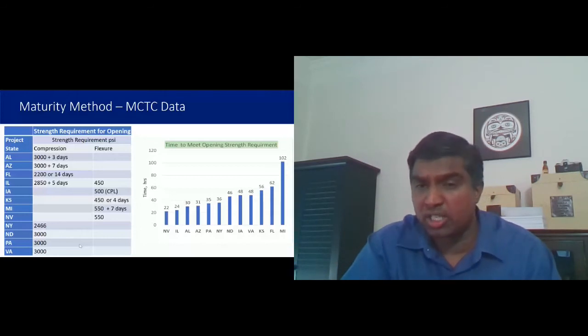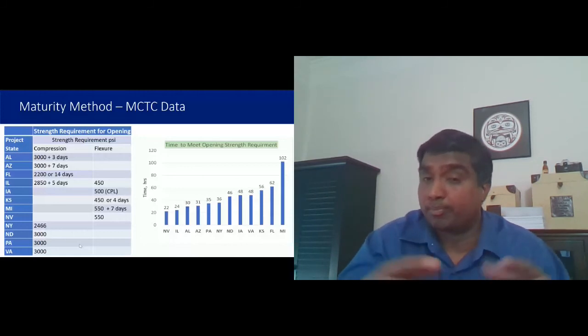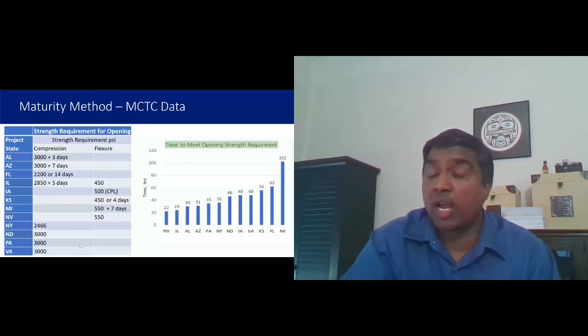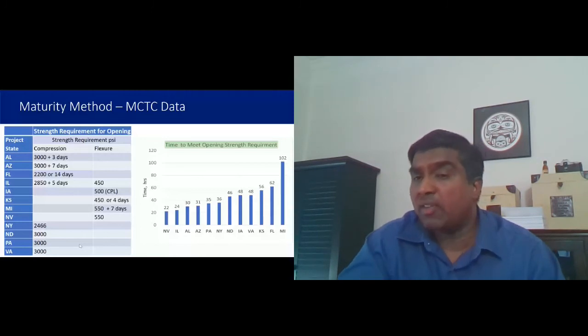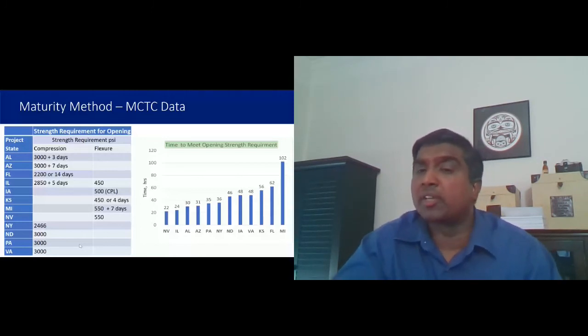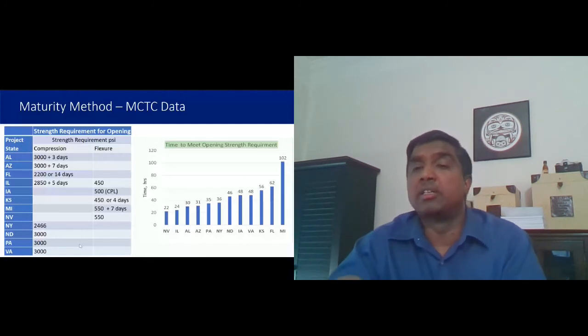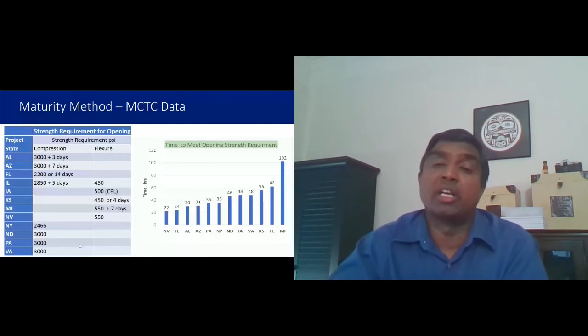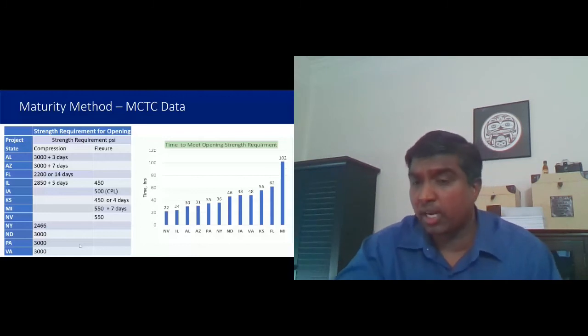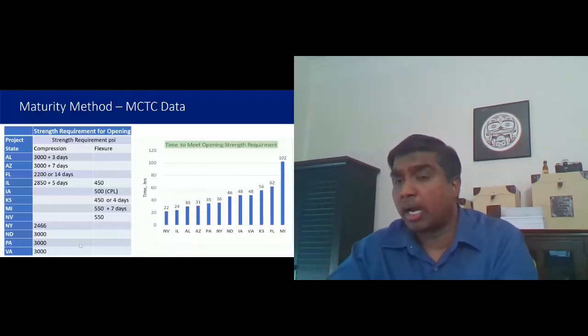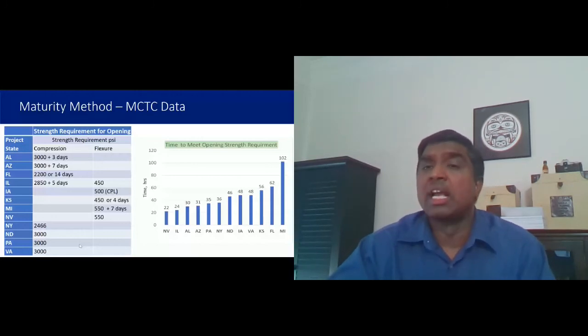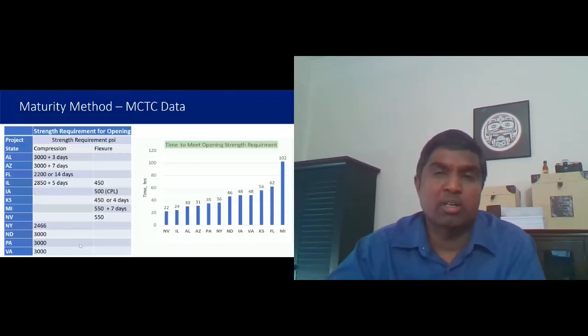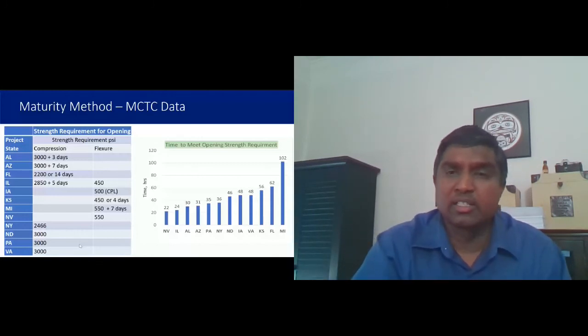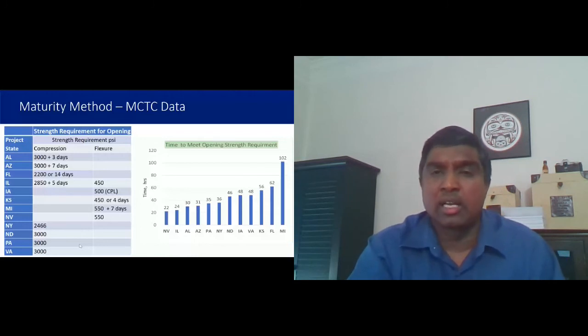So in this case, as you could see, Nevada actually, the project that I showed earlier on, the pavement reached a strength of 550 in literally a day. But even other projects, as you could see, in the majority of the cases, the pavements reached the opening strength requirement in literally a couple of days. Michigan, which is the very far right bar, says more than 100 hours. And that was because we were there in October of that year and the weather conditions were quite cold. So again, similar data. This is from Iowa.